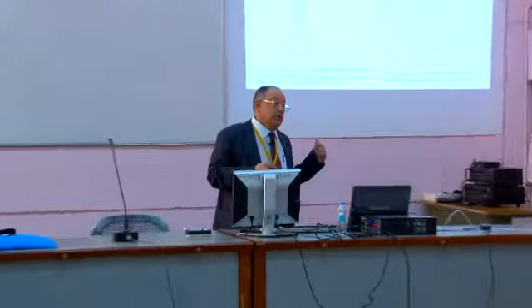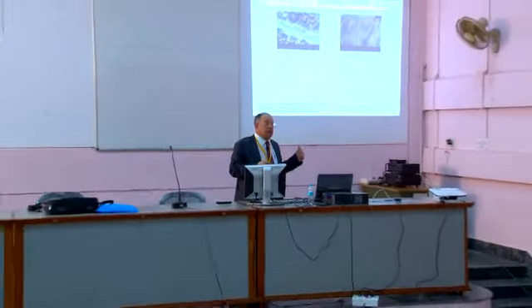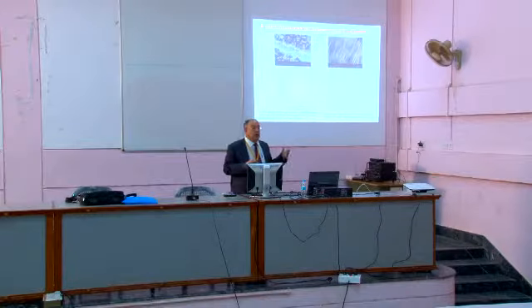Then we did some SEM photos. When I investigated under SEM, I found those additives formed on the surface, mostly because the oil contains calcium, phosphorus, sulfur and zinc.